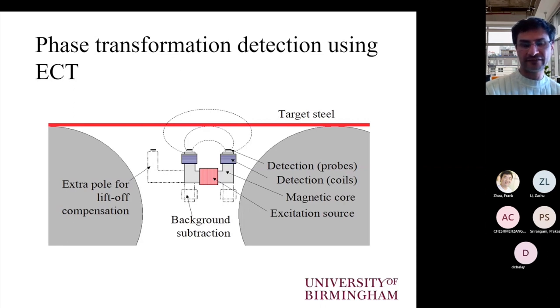So as long as the steel has a temperature which is below the Curie temperature of that grade, if any ferrous phase has formed, that will enable us to detect it with such an electromagnetic detector, provided that there are no significant lift-off variations as the plate or strip is moving along above the cooling bed. Of course, the conductivity effects will play a role, but they will have a lower effect in comparison to the permeability variations. So even though conductivity variations have a measurable and detectable effect, in ferrous materials, it's the permeability that dominates the signal.